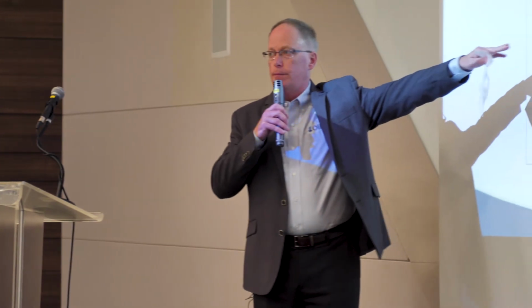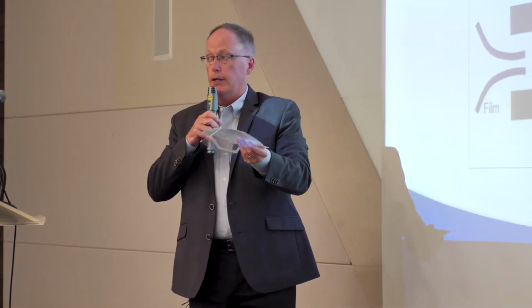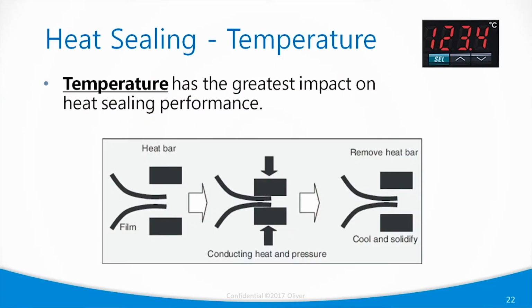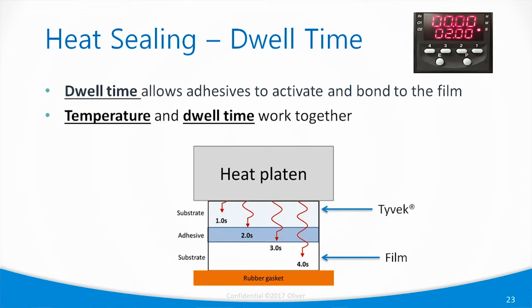Just visualize in your mind, it's a pretty basic process where you're taking a heated bar, you're marrying two materials together with heat, and then you're using some dwell and pressure as well, but you're just marrying the two together to get a heat seal. Temperature is the most important factor to pay attention to in your experiments. And then dwell time is the second most important factor after temperature. The temperature in your sealing process and the dwell time work together. Visualize it that way. You can use higher temperature and shorter dwell time to optimize, or you can have lower temperature and longer dwell time to make the same thing happen. You want to balance it out, and that's how you should look at it.